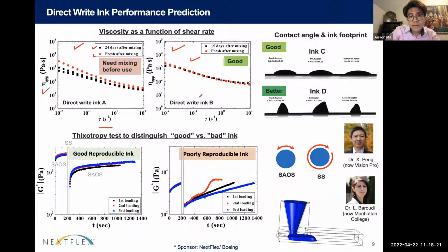And there's also another ink that we looked at. You don't need to worry too much about that one, at least for 15 days. You get the ink and it will print within that time frame, then it should be fine. So rheology is a good way to fingerprint the ink before you load it into the printer and realize that it doesn't work, right? Another way to make it work, if it does settle, is to remix it. You can throw it in a speed mixer to remix it before use. But this helps you identify how long a workable window I have for the material.